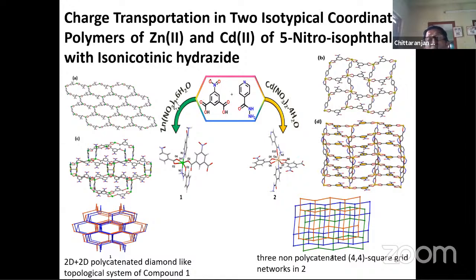On one hand, it forms the zinc complex, on the other hand, it forms the cadmium complex. Only the change of metal ions has changed the entire character of the complex system. You see, herein the polycatenated system is 2D plus 2D type, a 2D plus 2D polycatenated diamond-like topology, while this is a polycatenated 4-square grid type network. So the size of the metal matters: cadmium is 4d and zinc is 3d, so the size of cadmium is increased. That changes the feature of the framework, and thus every character will change.